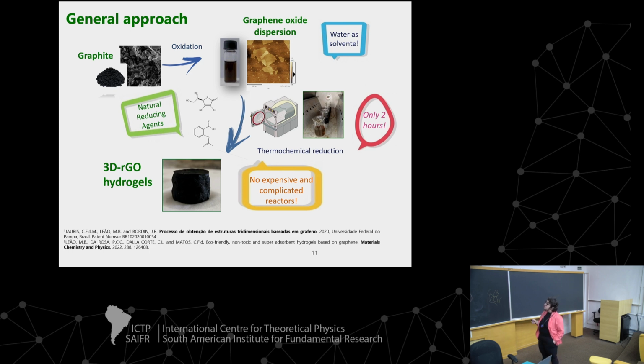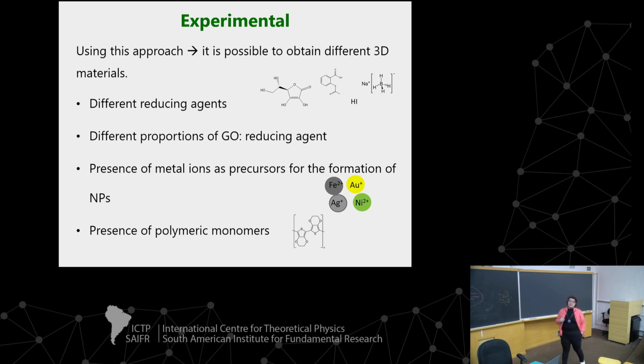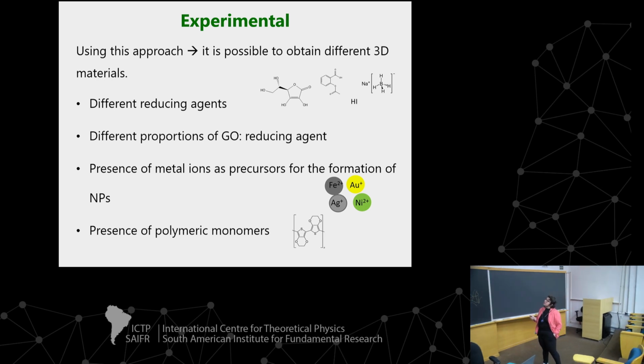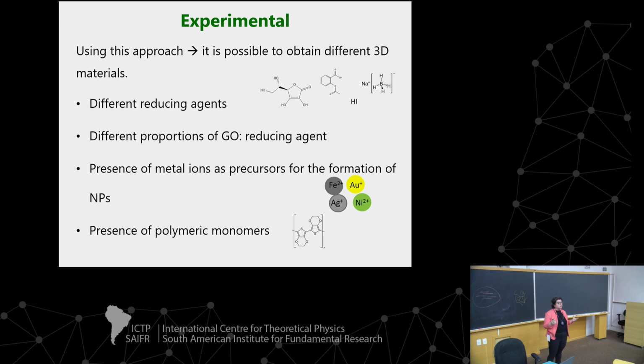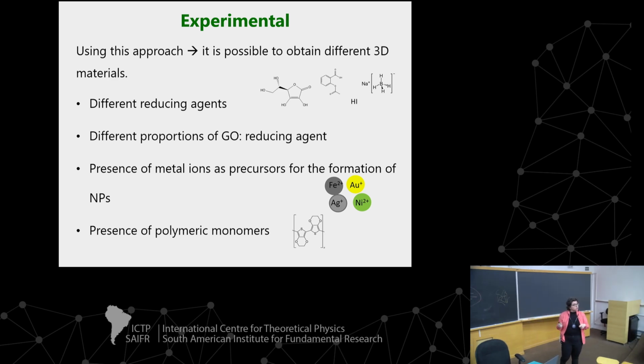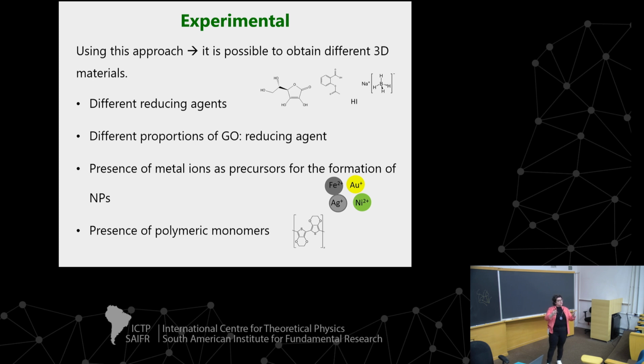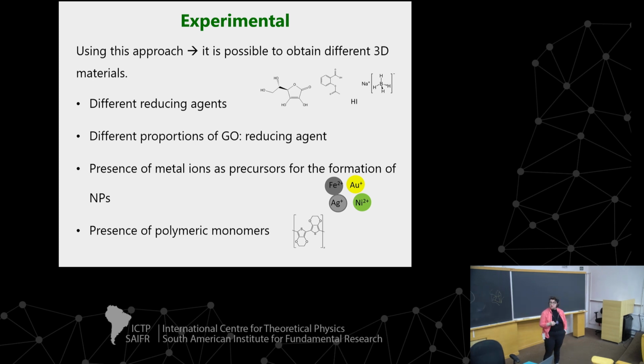This synthesis is not expensive, needs no complex reactors, and is at least 12 times quicker than the conventional methods described in the literature. So we patented this; it only uses water and natural reactants. Using this approach, we can modify the synthesis and obtain different kinds of 3D materials: using different reducing agents, different proportions of graphene oxide to reducing agent, inserting metal ions as precursors for the formation of nanoparticles, and also inserting monomers of polymers to create a 3D material with polymers adhered to its surface. We have different kinds of applications for this.